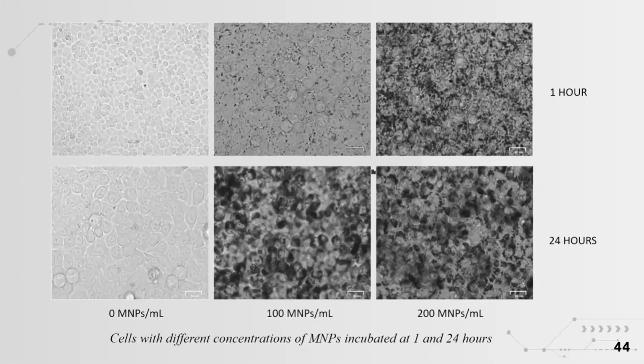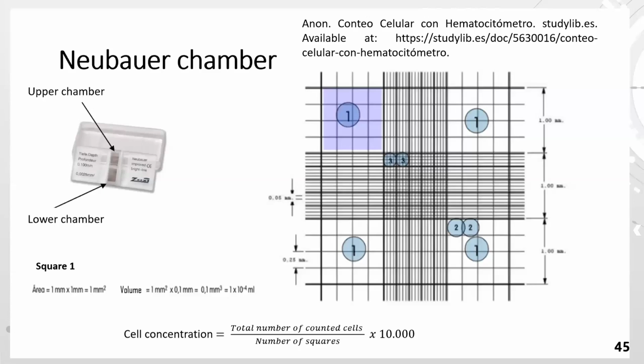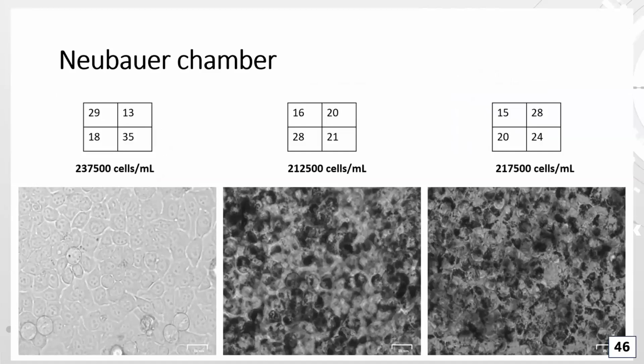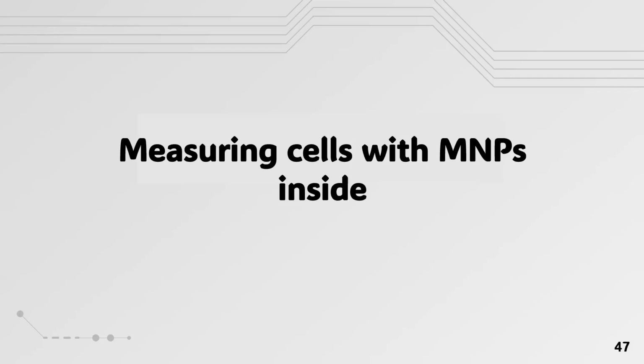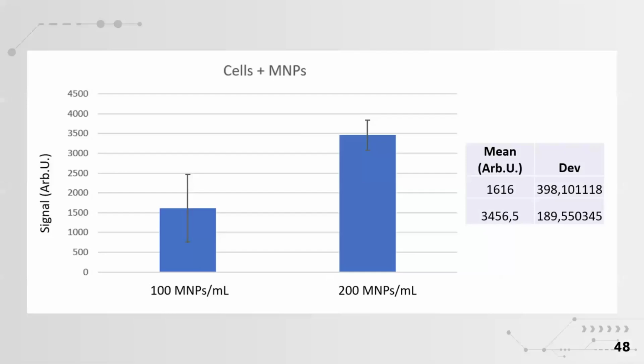As you can see in the confocal images, there is a clear difference between hour 1 and hour 24 after the incubation. It's clear that the cells were pretty hungry and have successfully eaten the magnetic nanoparticles. Now we did a cell counting using the Neubauer chamber, also called the hemocytometer. And as you can see, we have a pretty good amount of cells. Finally, we measured the cells with the magnetic nanoparticles inside, and these were the results that we obtained.